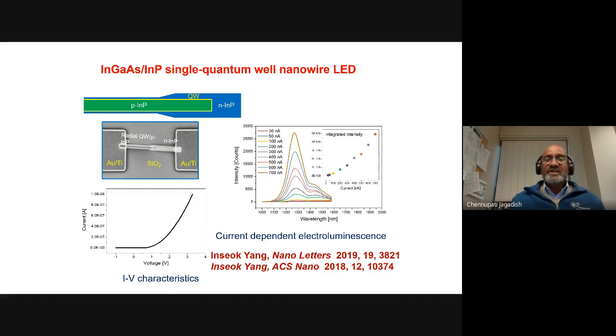So then he transferred these nanowires onto a glass slide and then tried to make contacts using electron beam lithography, gold titanium contacts, and then injected the current and looked at the light coming out of these ones.